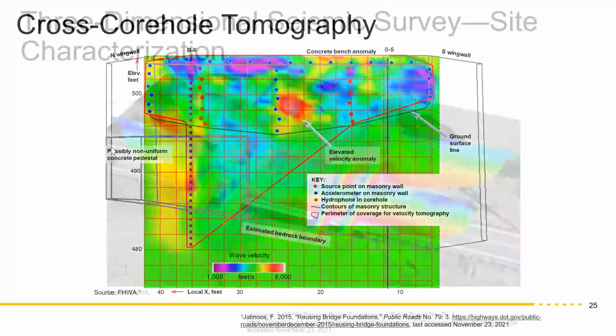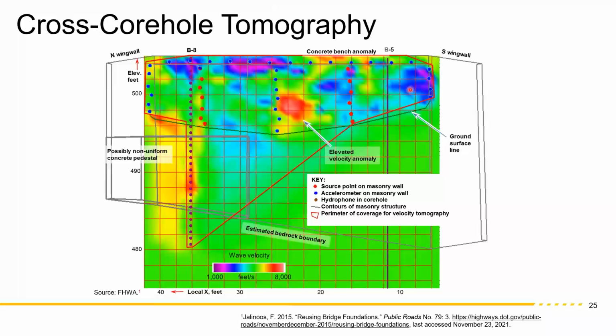Okay. Of course, if you have a pair of core holes, you can do cross core hole measurements. But here you need to have this, just like that cross hole sonic logging that Bernie showed. But here we're using geophysical methods, because of the distance involved. We use hydrophones and seismic sources, and then you use many different angles rather than just looking straight across. For every source, we have many different angles, and you can do tomographic imaging of the whole foundation, including the bedrock. And these were the issues with those holes that subsequently our federal lands office grouted.